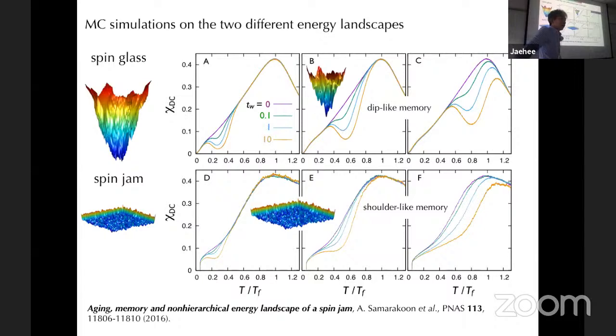But it looks like what you seem to tell us is it doesn't matter whether they're here or there. It's all the same thing. No. In fact, in your glass case, it probably depends whether I get trapped in a more excited metastable configuration or somewhere down there. No, even here it's not like all metastable states have exactly the same energy. They are very different. I'll show you. So it's a mix, kind of. You could say many spin glasses coupled together. I think it's a matter of degrees, right? So here, you start from here, you just flatten out, then you get this kind. So from here to here, if we can tune some parameters, it will be a crossover instead of some transition.